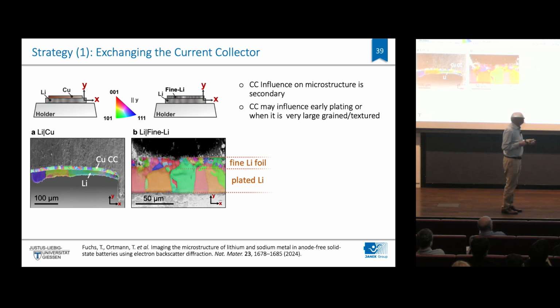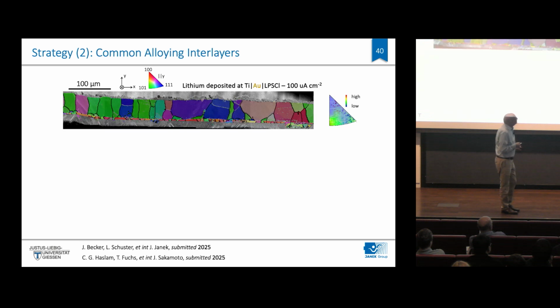So you see here the microstructure of a copper current collector, and the grains are pretty huge here, and we never found really a clear-cut correlation with the current collector. But what we found is, and it's known by work by others, for example, by Jeff Sakamoto, that if you have here the electrolyte and the titanium current collector and a little gold interlayer, gold dissolves in lithium, that the microstructure already looks a bit different.